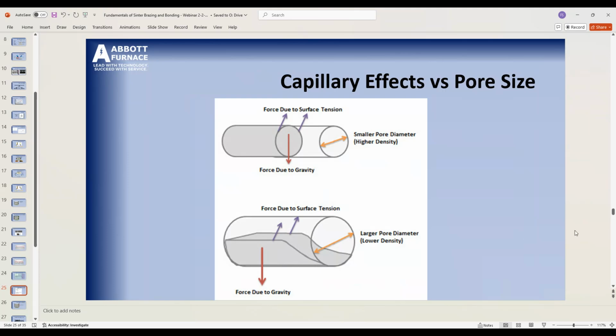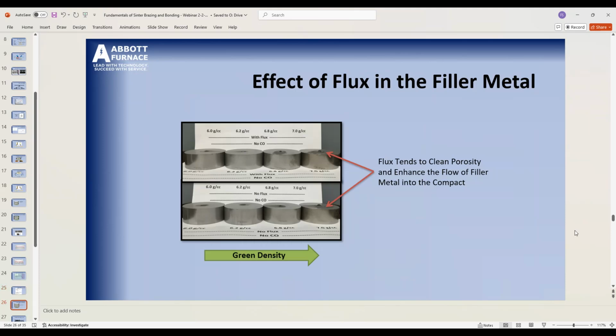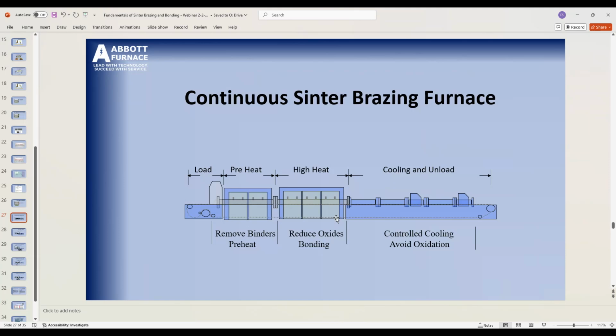So we want to be high in density so that we have control of where that's going to go. Okay, and so like I said, flux, you can see here above, here's with flux, you notice that we infiltrate all the way up through, and we even have some infiltration at 7.0. But if we take the flux out, it holds it at the surface at the higher density like we want. So don't use the flux.